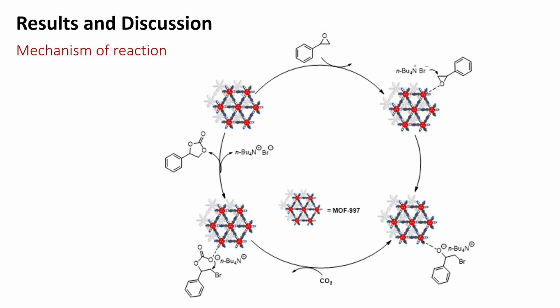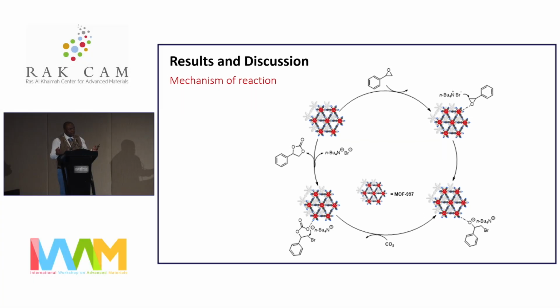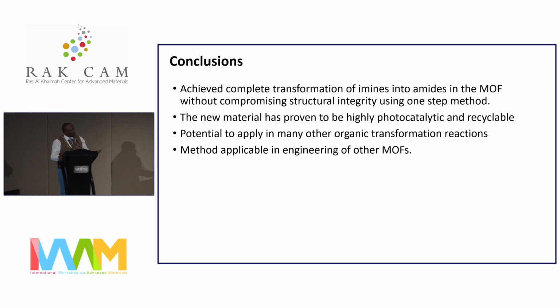So the mechanism is simply the MOF being able to open up the epoxide, activating the epoxide, so that there is a nucleophilic attack by the bromine from the co-catalyst, and then this opening enables CO2 insertion and then ring closure, leading to the regeneration of the MOF.